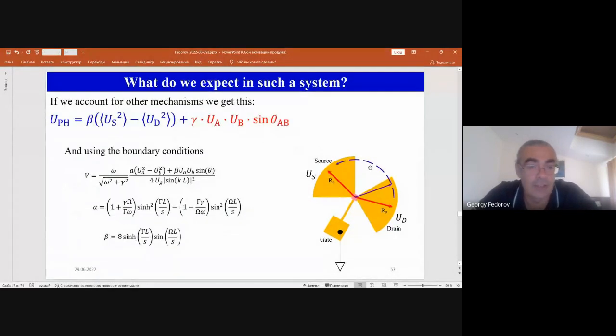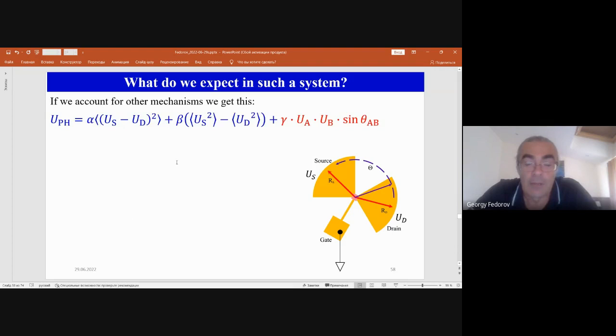So I just shrink it to these two terms. You have one term proportional to the difference of the square values of potential on source and drain electrodes, and another term which is proportional to two amplitudes of these potentials, not these mean values, and the sign of the phase difference between them. So this term is important, and it results from this interference of plasmons in the graphene channel. So in a more general case, you have three terms: mean square of the potential difference, difference of mean squares, and our nice term that describes the interference.